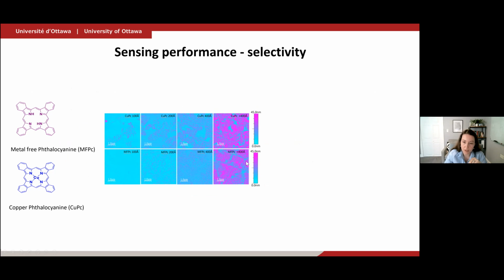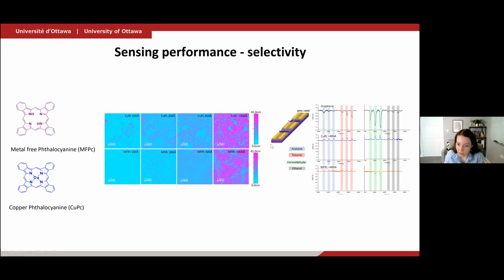And what you see here is atomic force microscopy imaging of copper phthalocyanines and metal-free phthalocyanines at different coverages. So we have control over how much we cover the graphene area. And what's really neat is that at different coverages, these sensors have different sensitivity towards the analyte they were trying to detect in such a way that you can build a table. And then you can have an array of these sensors. And the response of these sensor array is essentially a fingerprint for every single analyte that you detect.